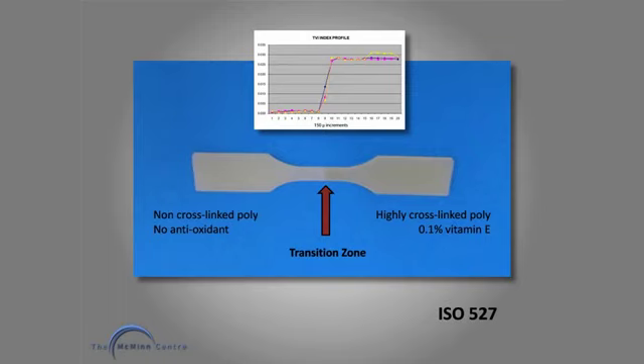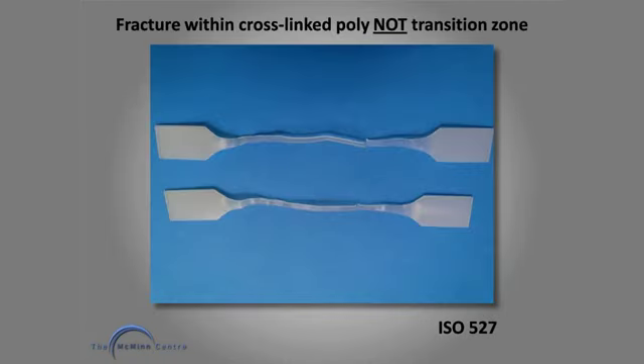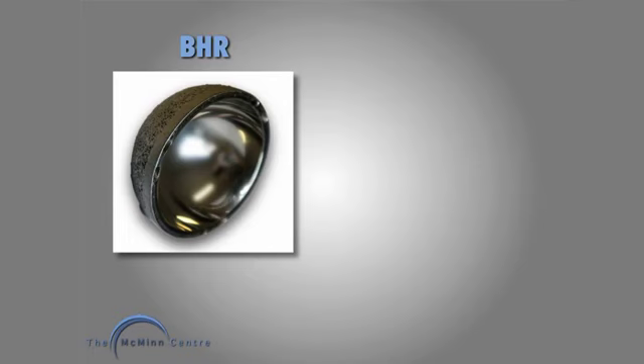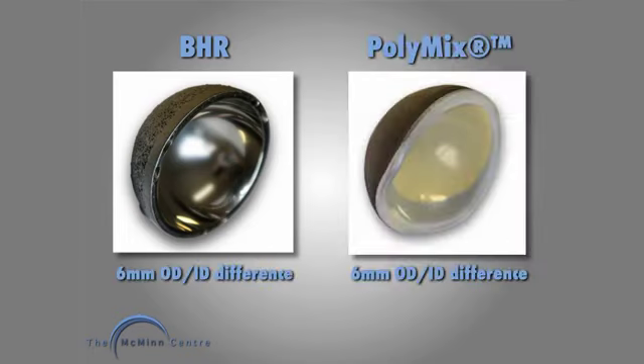Now you might think, molding cross-linked polyethylene and conventional polyethylene to each other might be a weakness at the transition zone. And you can see on the right the transvinylene index showing that on the right side there's highly cross-linked poly, and on the left side there is non-cross-linked poly. That has been formed into a standard elongation to failure test, ISO 527, and when you stretch these things to failure, usually the failure mechanism is fracture across the middle of the cross-link zone. Never fractures in the conventional poly, of course. So now we have Birmingham hip resurfacing and Polymix, both with 6 mm outer diameter, inner diameter difference, and we are about to start the clinical trials on Polymix.